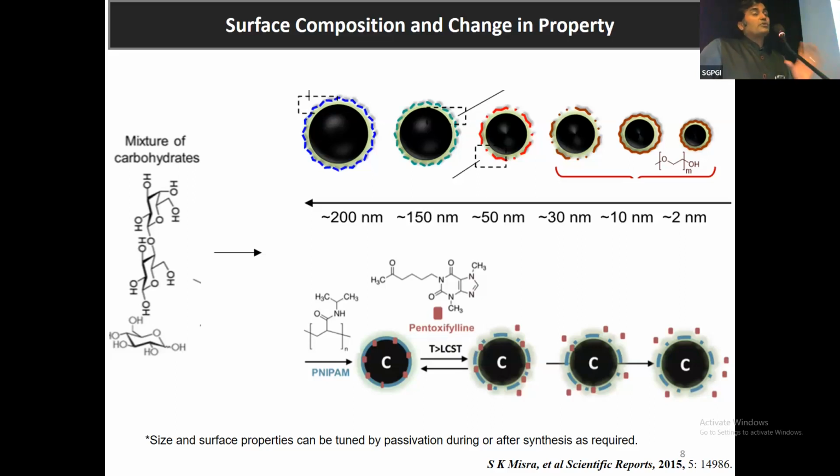Now, if you are doing co-preparation, you can even tune the size. The size could vary from 2 nanometers to 200 nanometers. That also is very reproducible and the yield is also very nice. So it depends on whether you want to use it for just biofluid purposes, or you want to deliver some content inside the cell. You can decide, and based on the pre-decided composition you can get a size, right? In general in nanomedicine, the concept is that if you want to deliver something inside the cell, then the size should be close to 100 or less than 100, because of the leaky vasculature, like in the case of cancer, right? If you want to deliver a drug loaded on these nanoparticles, it has to cross that leaky vasculature, so it should be less than 100. But in some other cases, even larger ones would work, where you don't want to go inside the cell, right? So size variation can be done.